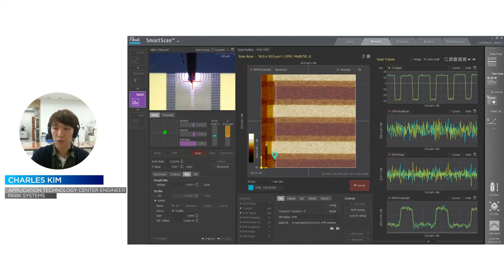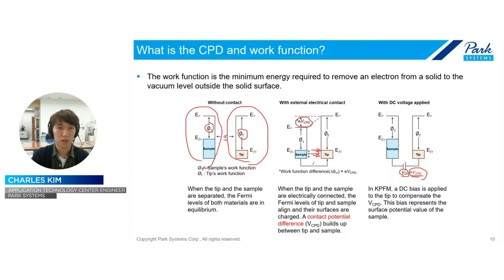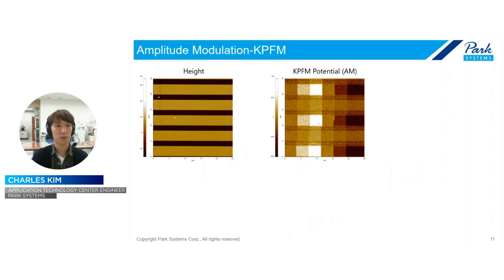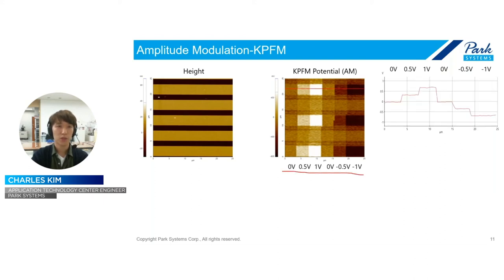And also, to save time in this talk, I already measured the KPFM image before. So it's the same as before in the EFM. I used 6 different sample biases. So when I draw the line according to the different sample biases, when I apply zero, it shows almost zero potential. When I apply 0.5, it's near 0.5, but because of the averaging, it has a little bit smaller value. But anyway, when I measure 1 volt, it becomes double.